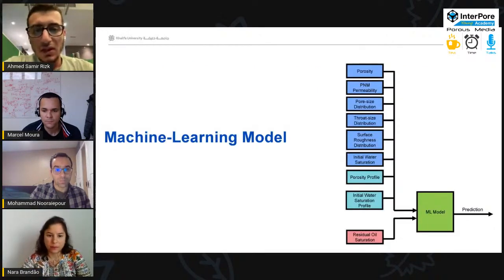All of these parameters are passed through a machine learning model for training and testing. The first parameter is, as we said, porosity. Then we have the permeability, the pore size distribution, throat-size distribution. We have the surface roughness, initial water saturation. We have the porosity profile and the initial water saturation profile as well as the corresponding residual oil saturation for each sample.